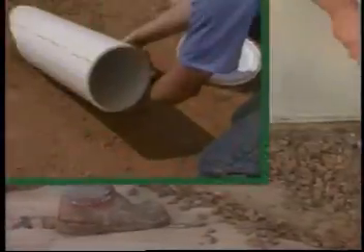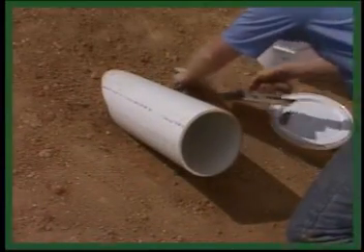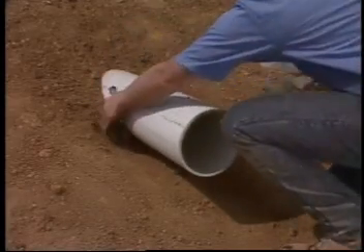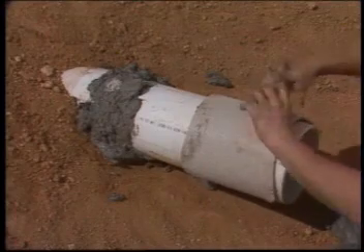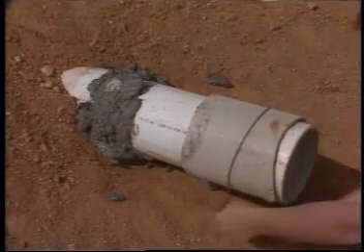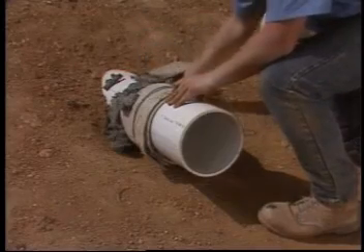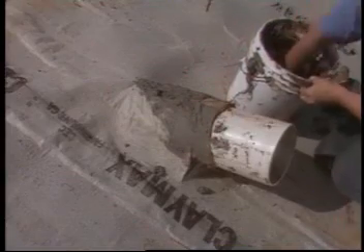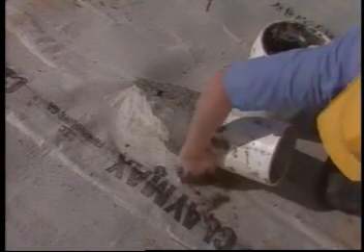To seal around pipe penetrations, again, excavate a small notch into the subgrade around the penetration. Backfill the notch with granular bentonite or bentonite mastic. Then, cut the GCL to fit around the penetration as snugly as possible. Apply more bentonite mastic to seal the GCL to the pipe. Finally, apply a secondary collar of GCL and another coat of bentonite or mastic to complete the seal.